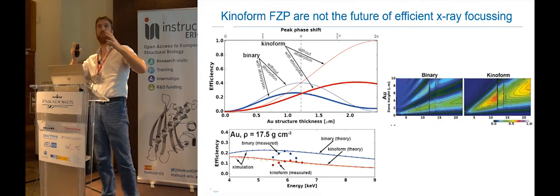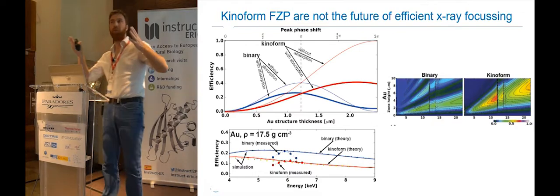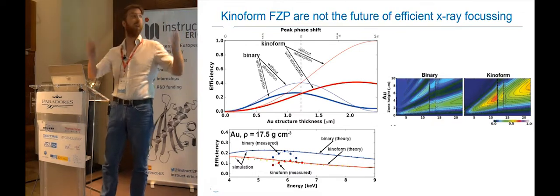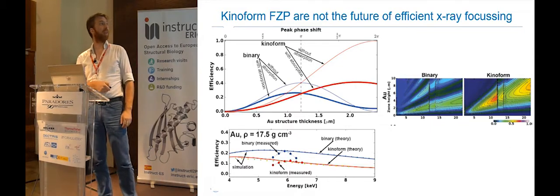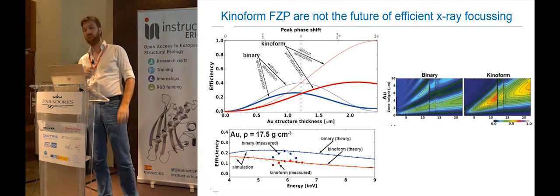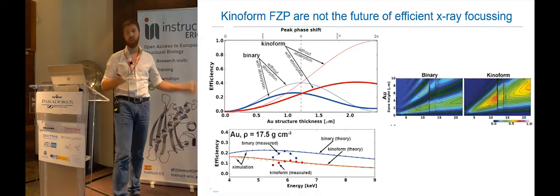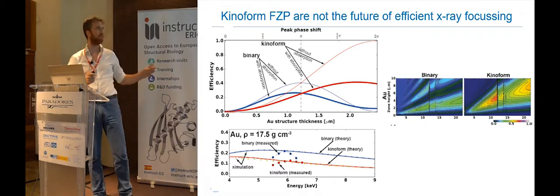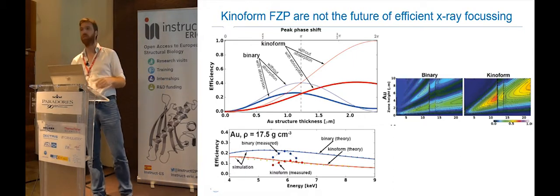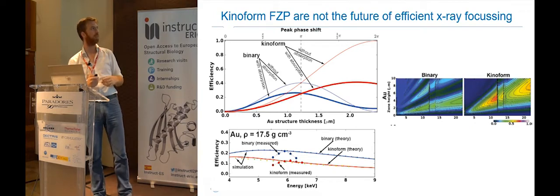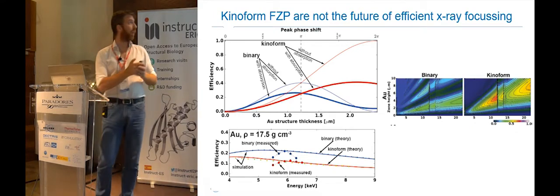So if you want to achieve a zone width of 50 nanometers, it's just not going to stand. And it will only work at around 10 keV or so. We've tested it, we've simulated many materials. So essentially, if any of you is into zone plates, don't do this.